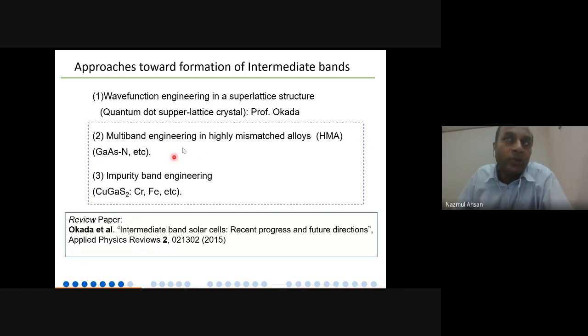So my pointer is made of gallium arsenide, but here I'm using the pointer of Microsoft PowerPoint. But in reality, we use a gallium arsenide LED. So that's gallium arsenide, and we use this material for optical communications and other things. And if you change the arsenic a little bit by nitrogen, this kind of material we call a highly mismatched alloy because they are very different in size. Nitrogen is a very small atom, and arsenic is a big atom. So this mismatch we call highly mismatched.